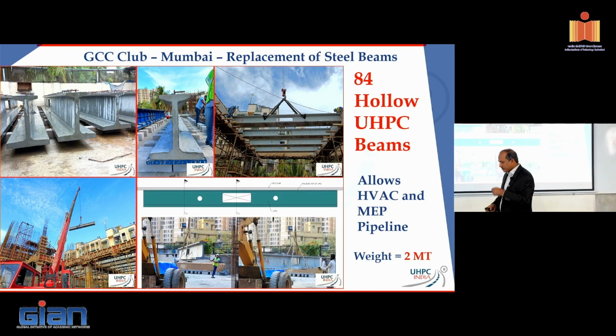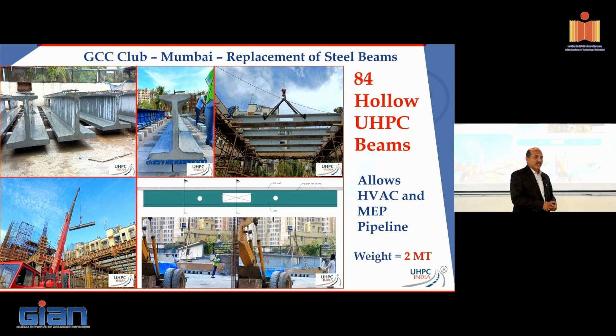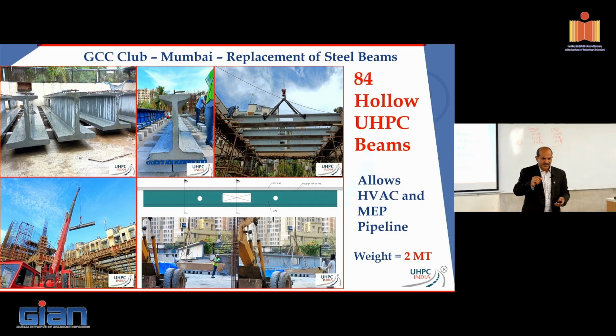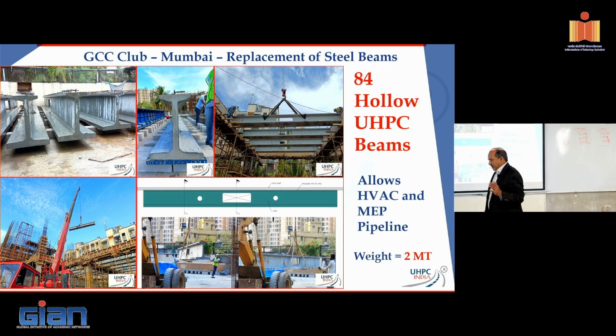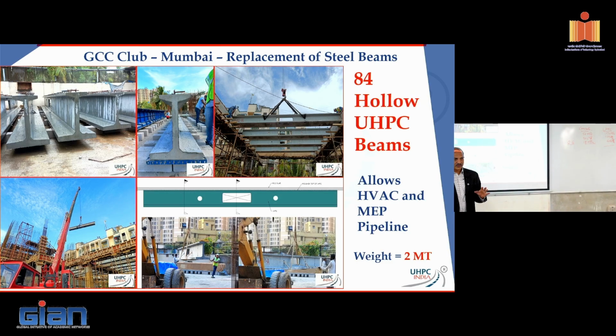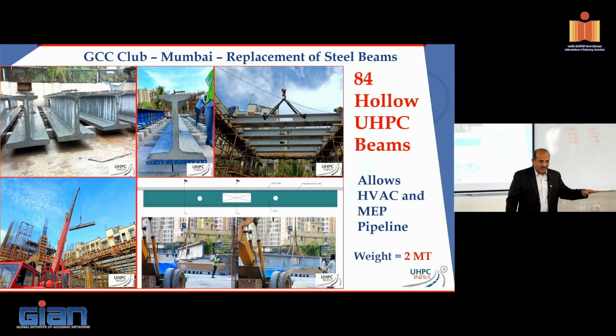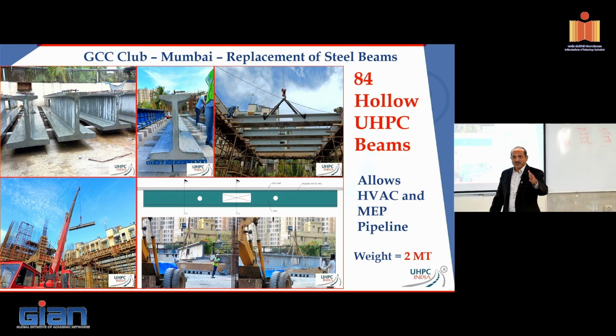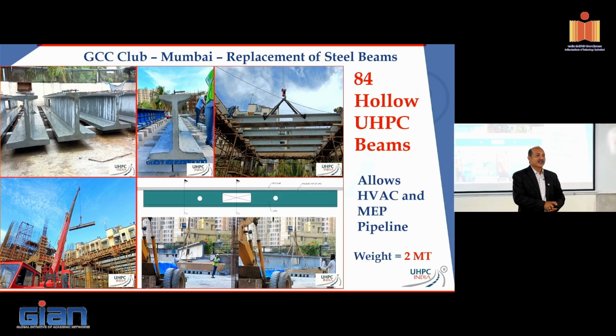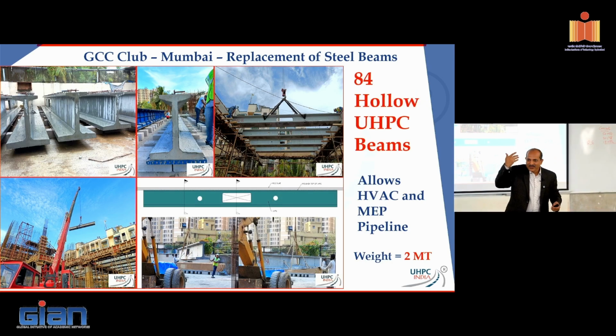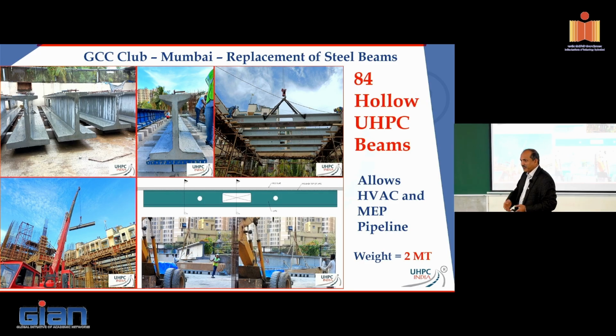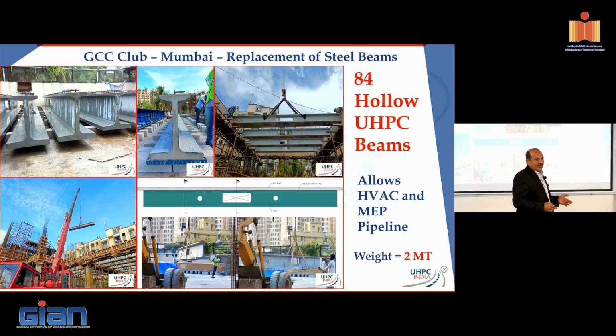But for building systems, we ran a lot of tests by adding a bit of polypropylene fibers along with the steel fibers, a very minute bit. So we went one by one, and what we found is, by the time you add 0.2% of PP fibers along with the UHPC, you have excellent fire behavior. Why? Because PP fibers melt around 100 to 150 degrees Celsius, and they create these fissures for the steam to escape. So that is why it improves your fire behavior sufficiently. And Professor Kodur also propagates this, that mix the fibers. Correct. Steel along with polypropylene.